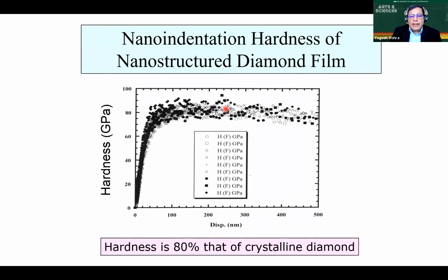So thinking about application now, I did state that your crystalline content of diamond goes down a little bit. The question is, how does it compromise the properties which we are used to with single crystal diamond? And this graph kind of answers that question. Here, what we have done is plotted the hardness of the material in a nano indentation experiment where we push an indenter into the surface of the nanocrystalline diamond film. And the interesting thing to note here is that you retain up to 70 to 80% of the hardness of diamond, at the same time keeping the nano smoothness of the diamond coating on the material.